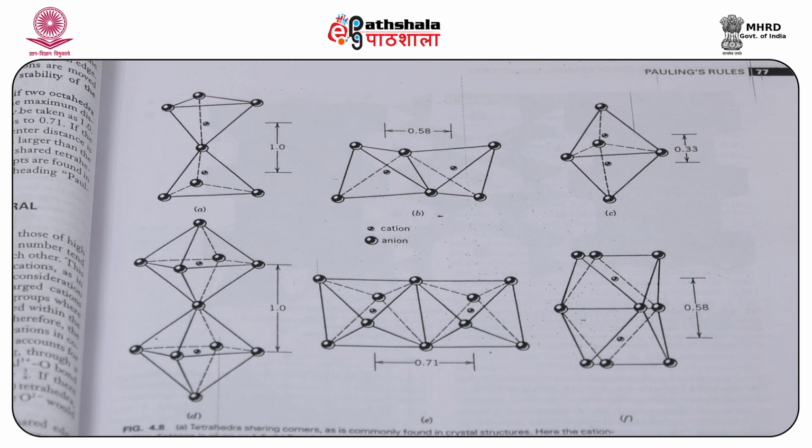This accounts for the lack of Al-O-Al structures and tetrahedra bonding, though bridging oxygen is common in many silicates. The Al3+ that is bonded to oxygen in tetrahedral coordination has an electrostatic valence of 3/4. If there was a bridging oxygen between two AlO4 tetrahedra, it would mean 2 into 3/4, which is equal to 1.5, and the O2- would not be satisfied.